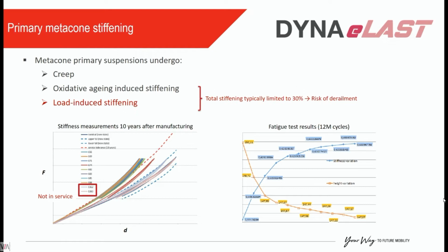This suspension undergoes creep and it undergoes oxidative aging during its lifetime, but it also experiences this load-induced stiffening. Just to evidence this, I have these force deformation curves of elements that were new. This would be the new curve, nominal new state. And then we have curves for parts that are 10 years old. Some of them have been in a warehouse and some of them have been in service. The ones in the warehouse are here, they stiffen. That's something to be expected because time goes by, but they are still within tolerances actually.